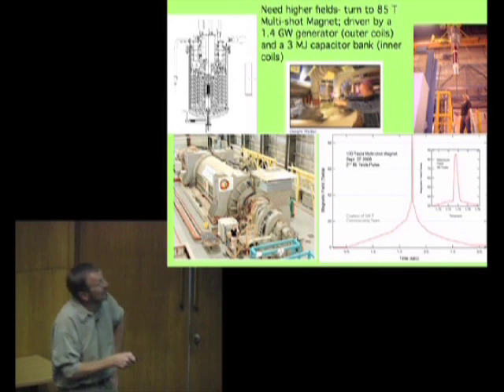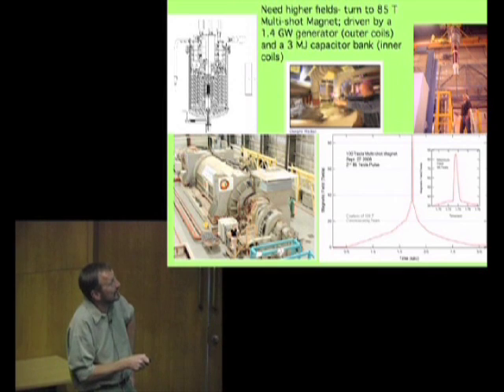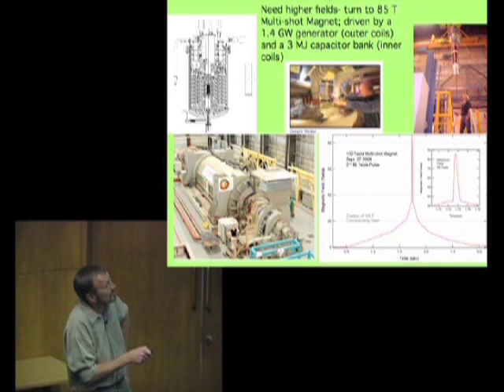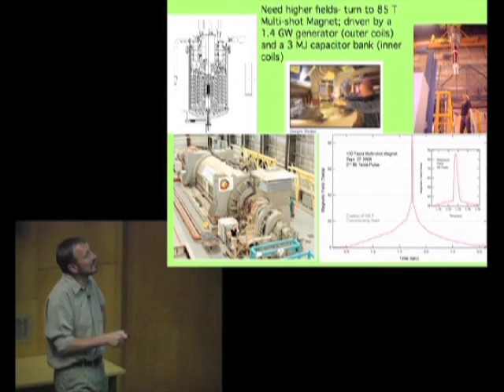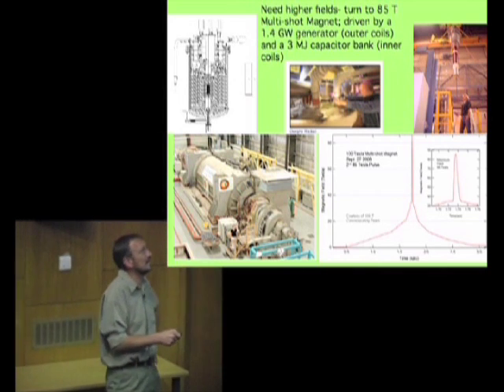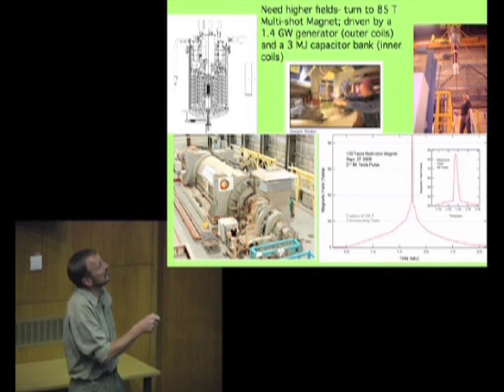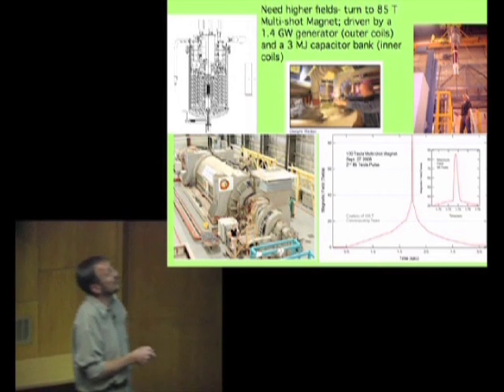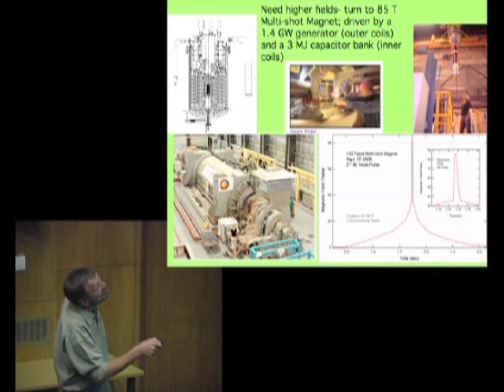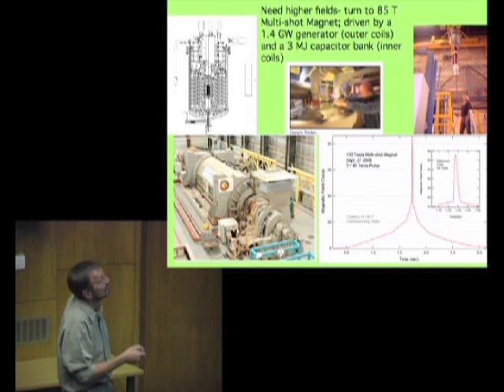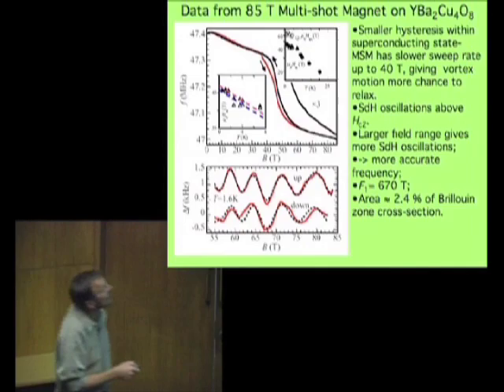We connect it to a capacitor bank charged up to 13.5 kilovolts, and that gives us this spike of magnetic field on the top. This is an enlargement of the center. So those two together presently give 85 Tesla. After some modifications to the inner magnet in the autumn, they will go to a full 100 Tesla. There's a human being by the top of this tank, so you can see the scale of this again.